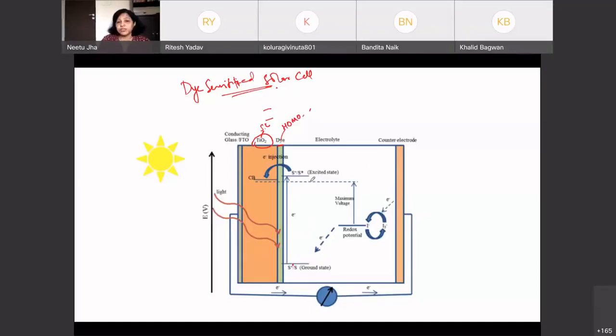Now, if we want to use it for electricity, I do not want this electron to go back and recombine with the hole. I do not want that. So how to stop that? That is the main trick, how to stop that electron from going back to the ground state. Now we also know that the band gap of a semiconductor can be changed by changing the size of the particle. So you have to play around in such a way that the conduction band of TiO2 is lower than the LUMO of the dye, and the electron can be transferred from the LUMO to the conduction band of TiO2.